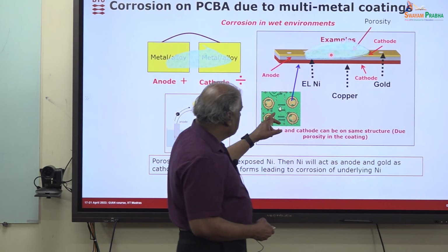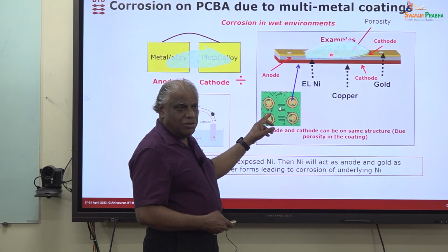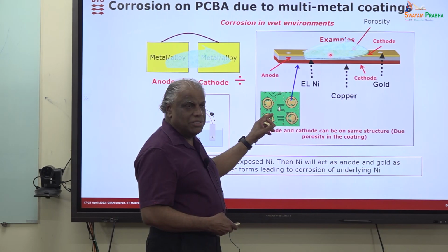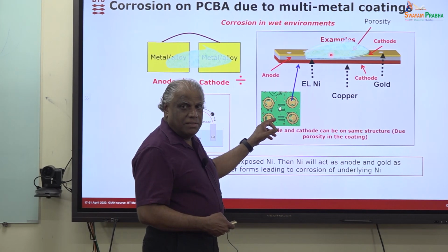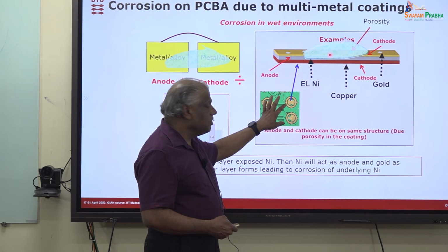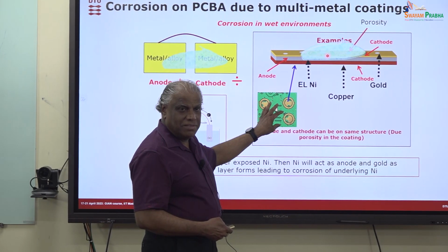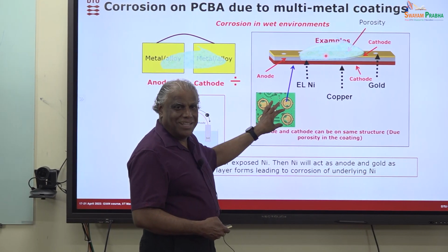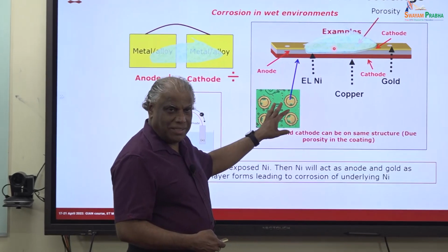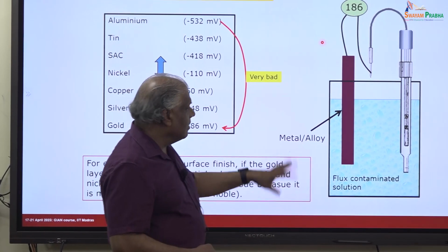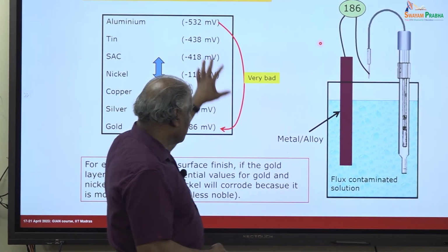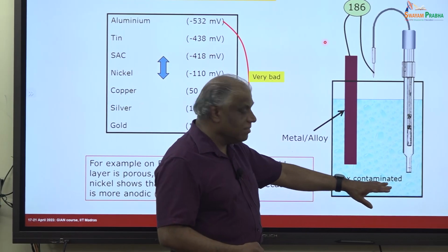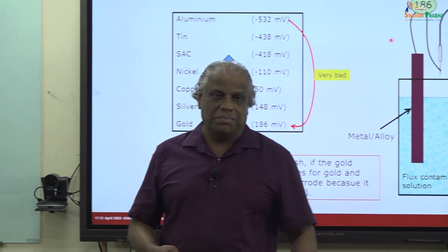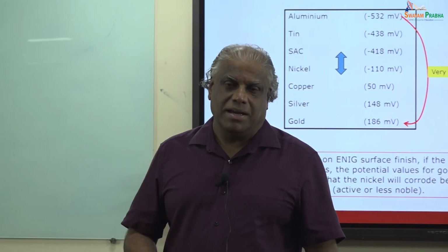When they manufacture this PCB, in order to do the soldering process and things like that, they need to use a chemical flux. That chemical flux will have some residues which are sitting on the PCB surface. That is a contamination, that's the residue, not the sodium chloride or anything. And that's the reason that they do this experiment and make this electrochemical series or galvanic series in the flux contaminated solution. There are typical flux systems and they do that.